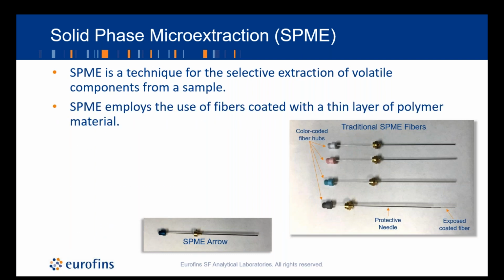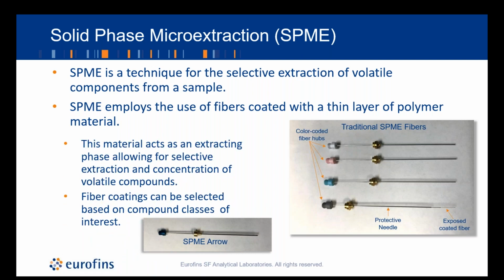SPME employs the use of fibers coated with a thin layer of polymer material. This material acts as an extracting phase, allowing for the selective extraction and concentration of volatile compounds. This can improve our sensitivity as we are concentrating these compounds before they are introduced. As well, it allows us to work with complex sample matrices as we can selectively choose our fibers to look for compounds of interest and help us avoid matrix interference.